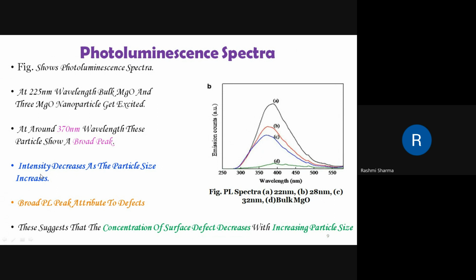Intensity decreases as the particle size increases because, as I explained earlier, it is due to defects present at the surface of the particles. As the size increases, the defect concentration decreases, due to the decrease in surface to volume ratio. So this suggests that the concentration of surface defects decreases with increasing particle size. The intensity of blue luminescence also decreases with increasing particle size.